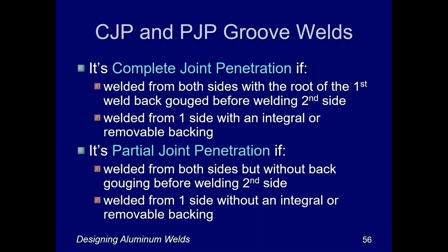Now, how do you know if it's a CJP or if it's a PJP? Well, the basic rules are, with small exceptions, it's CJP if you weld it from both sides. First you weld it on one side, you flip it over, you back gouge the crud and stalagmites drooping out of the backside, and then you weld the backside. Or you weld it from one side with an integral or removable backer on the backside to prevent the crud and the stalagmites from accumulating on the backside.